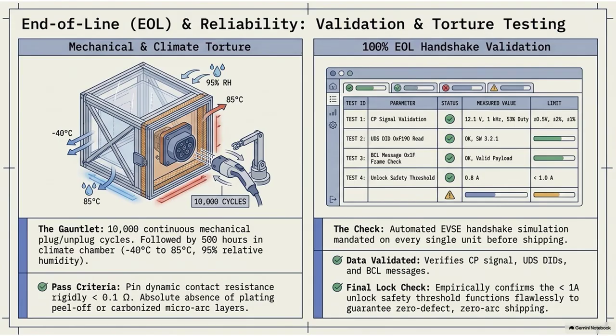But they aren't done. After the robot finishes 10,000 insertions, when the metal pins are thoroughly worn out, scratched up, and stripped of their protective coatings, they take that entire plug assembly and throw it into a climate chamber. Yep. They plunge the temperature down to negative 40 degrees Celsius, which is brutal, Arctic deep freeze conditions. Then they rapidly bake it up to 85 degrees Celsius, which is 185 degrees Fahrenheit.